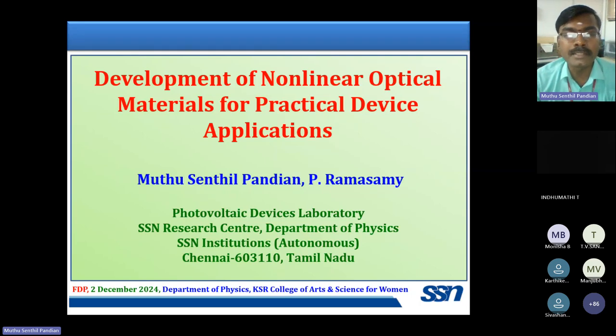High quality single crystals are of great importance when it comes to device making. In this lecture, I am going to present a method which gives you crystals of very high quality. All the crystals you are going to see in my lecture are grown by basically three different techniques, namely the slow evaporation solution technique, SEST. In a very small size beaker, we have grown a lot of technologically important nonlinear optical organic single crystals, but we cannot use them directly for practical device application because when we grow crystals by SEST, we can grow only a small size.